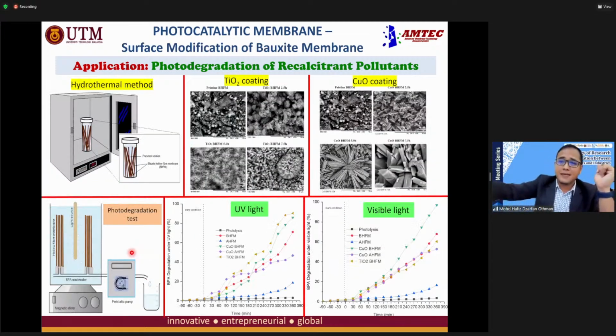Just imagine if we have sunlight, and this photocatalytic membrane can react to the sunlight and degrade the pollutant. At the same time, it can carry out the filtration process. With the bauxite membrane coated with TiO2, when exposed to UV light, we can degrade more than 90%. With copper oxide exposed to visible light, we can degrade almost 100%. So we can further boost the performance of the membrane if we coat another layer on top of the bauxite membrane. This is how we enhance the reaction sites for photocatalytic degradation.